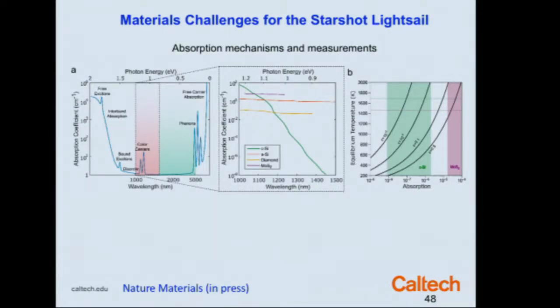Okay, what about the actual physical characteristics from an optical sense of the materials? All the materials we're talking about are dielectric materials. They have wide energy gaps. Therefore, they have absorption at short wavelengths. They have coupling between the optical phonons and the lattice at long wavelengths, the so-called Reststrahlen band or phonon-polariton modes. They also have defects that give rise to color centers, that give the crystals physical color due to trap-to-band transitions. So these are the generic characteristics of these materials.